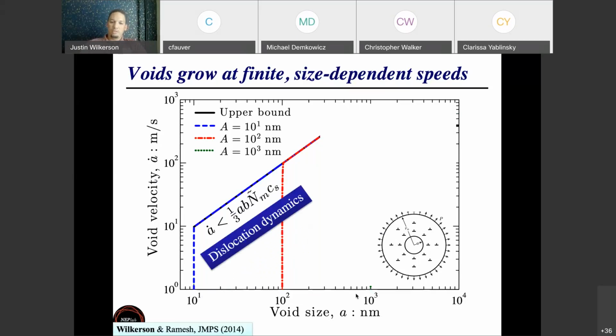So what you find for very small voids is that their kinetics are dictated totally by the upper limit on the dislocation velocity. What happens is you have a very unstable stress situation for the dislocations around the void surface, especially in spall. And right away, because void growth is fairly unstable, you drive these dislocations at the fastest rate that they can possibly go, which is the shear wave speed of the material. And then that creates the upper limit on how fast these voids can grow.